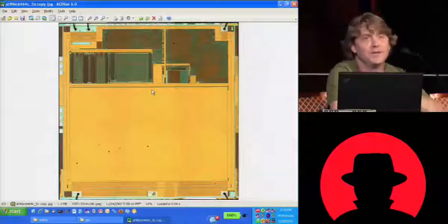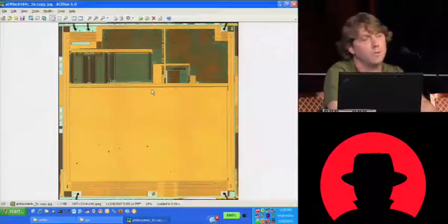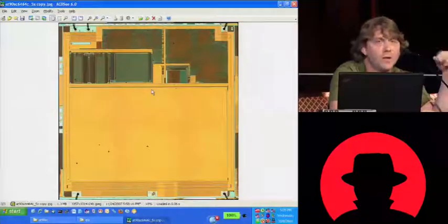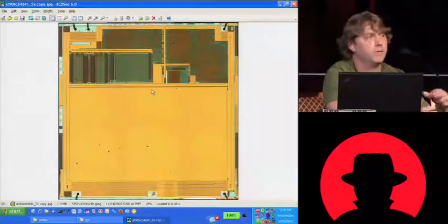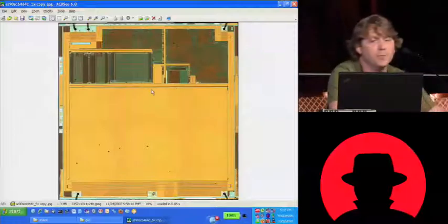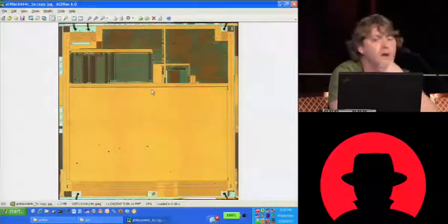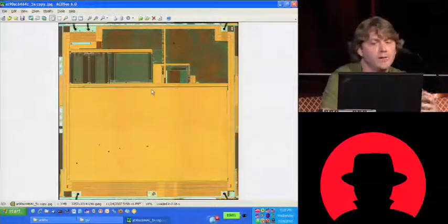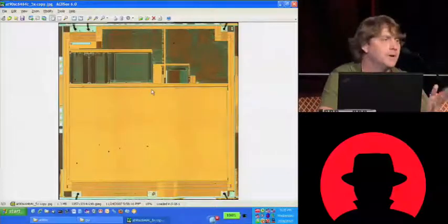So basically we start to strip the chip down. We strip it layer by layer. Top metal, strip it off. Actually, one of them you're going to leave it alone. Maybe you'll polish it down a little bit, to get rid of some of the passivation. Sometimes the die will look clearer in your images if you mill it for a little bit on a lapping machine. Just lap it down a little bit. Remove a few microns of the passivation, that very top oxide. So you strip this down layer by layer, and then you do photomosaics of the areas where you think they might be, and you're looking for some flip-flops that are going to have a common clock.